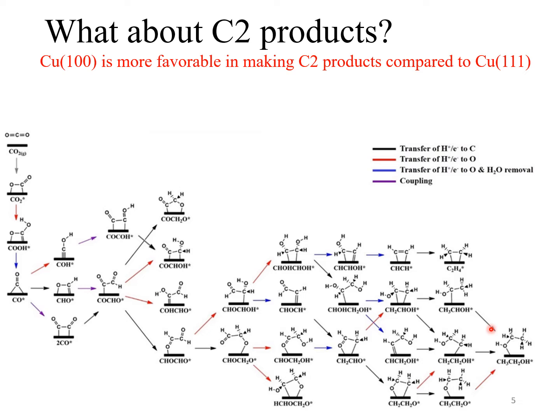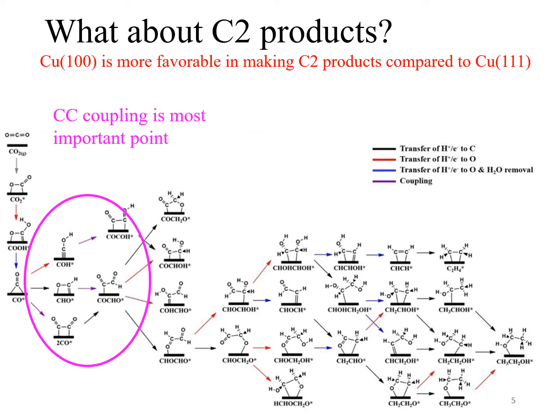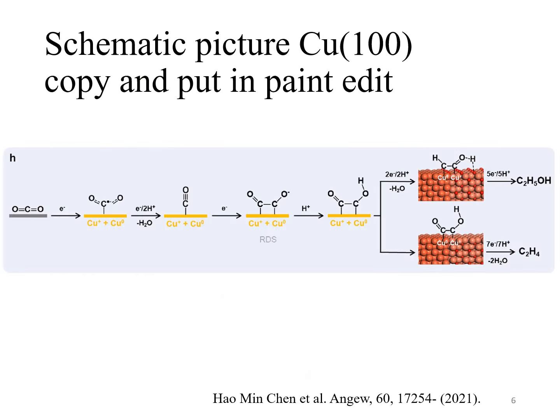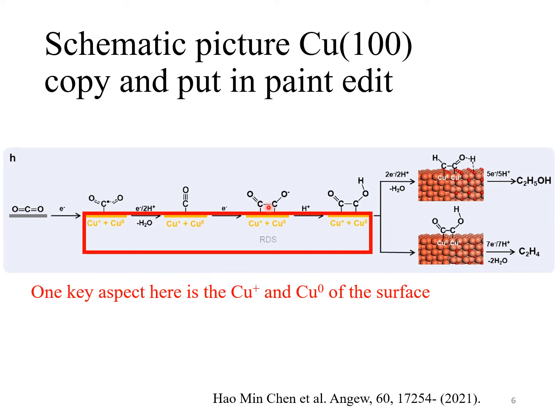It is known that copper 100 surface is more favorable compared to copper 111 surface in making these C2 products. And we believe the CC coupling is the important point. If one looks at this Angewandte review paper, we see one important aspect mentioned concerning the rate determining step of this CC coupling forming CO-CO, and that is this coexistence of copper plus and copper 0, oxidation state +1, and 0 copper on the surface to promote reaction of CC coupling.